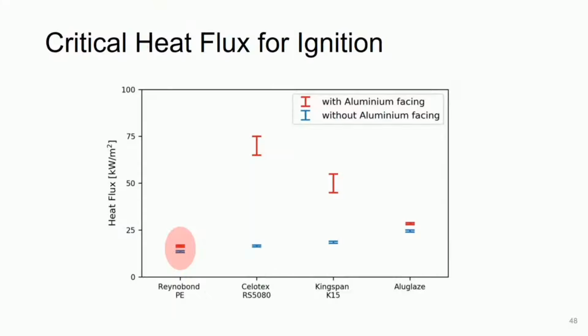If I highlight the Reynobond results, we can see that the Reynobond PE product will ignite at comparatively low heat fluxes. This means that, in the configuration that we tested, it would be expected to ignite in most any cladding fire scenario. We can also see that the removal of the aluminium facer, moving from the red data to the blue without, makes the Reynobond PE only slightly more susceptible to ignition, so not much of an effect. The same is true for the Aluglaze window infill panels, albeit with a slightly higher critical heat flux, both with and without the aluminium facers in place.